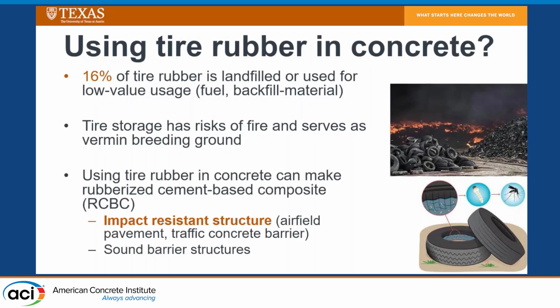There's been research that has shown that when you utilize crumb tire, so basically ground tire, in concrete, this can lead to improving the impact resistance. And this is where we were coming from, because this project was funded by the Texas Department of Transportation. So we were looking at this for impact resistance, particularly with respect to the application for using it in traffic barriers. There's also been work that has shown that when you start using recycled crumb rubber, this can also improve the acoustic properties of your cementitious composites.